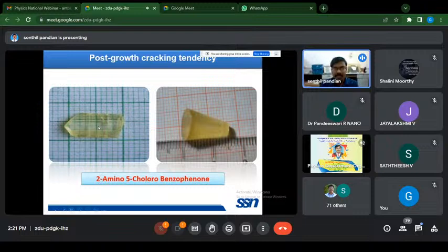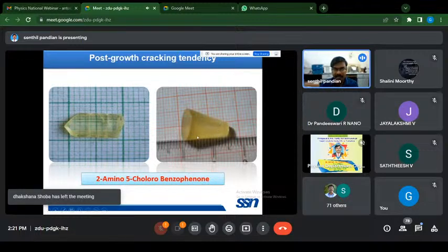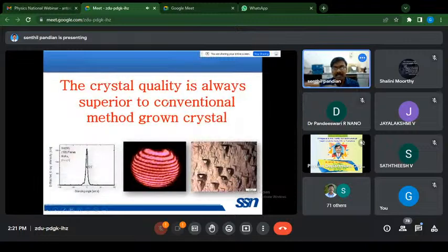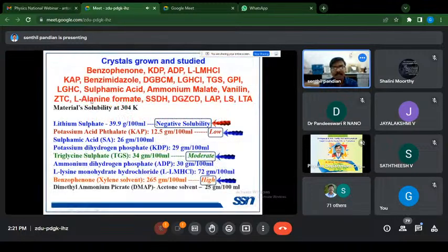So this is the conventional method grown crystal with a lot of micro cracks and milky opacity. And the same crystal we have tried in the SR method, and we have successfully grown this much larger size of transparent crystals. The crystal quality is always superior to the conventional method grown crystal. This we have confirmed with several characterizations like UV-NIR, birefringence, optical transmittance, Vickers microhardness, dielectric, HRXRD, density, and so on. So far, by this method, more than 200 crystals have been grown.